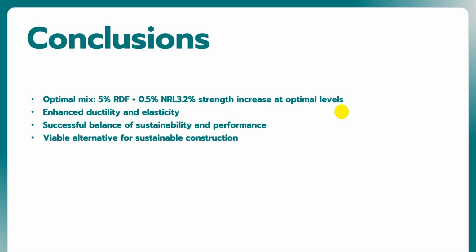As for the conclusion, we found an optimal mix design at 5% RDF with 0.5% NRL, which surprisingly increased strength by 3.2% over the high-strength concrete, and which can enhance ductility and elasticity. And the product can balance performance and sustainability. That's why for our sustainable solution, using RDF and NRL can be the driver for our sustainable construction environment.